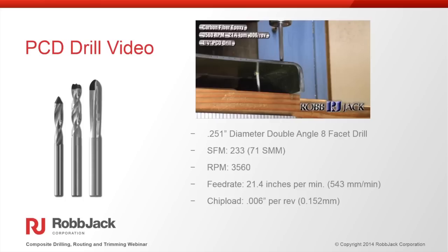So here I'm going to show a video, and remember the video may not show up at full speed on your screen, but essentially what we're doing is we're taking a 1/4 inch, 251 diameter double angle PCD drill. It's going to be going at 233 surface feet per minute, which is 71 surface meters per minute. Or for RPM, it would be 3560 RPM, and a feed rate of about 21.4 inches per minute, and with about a 6 thousandths per revolution advancement.